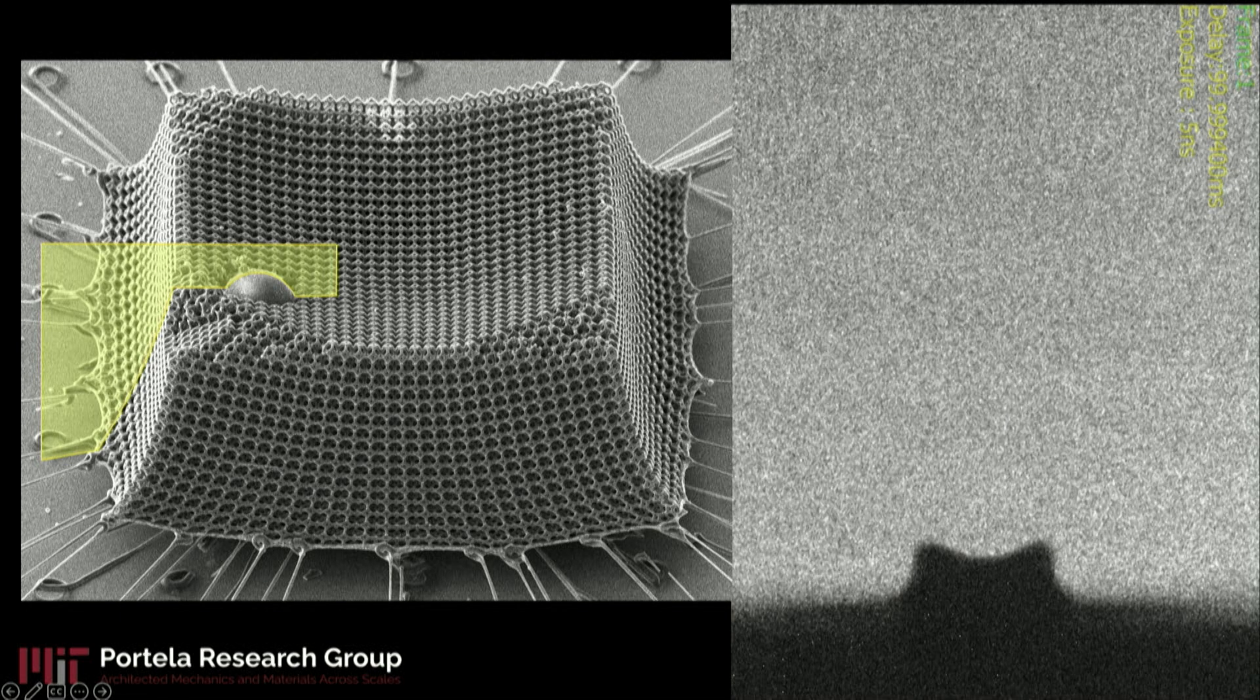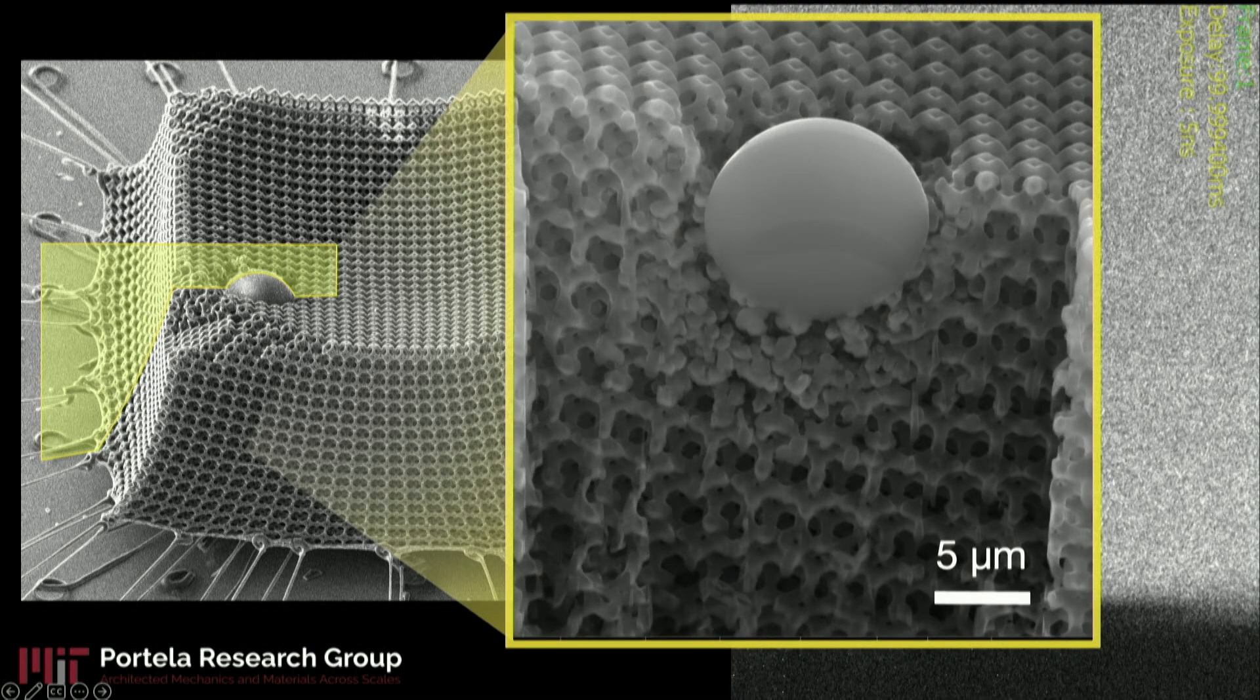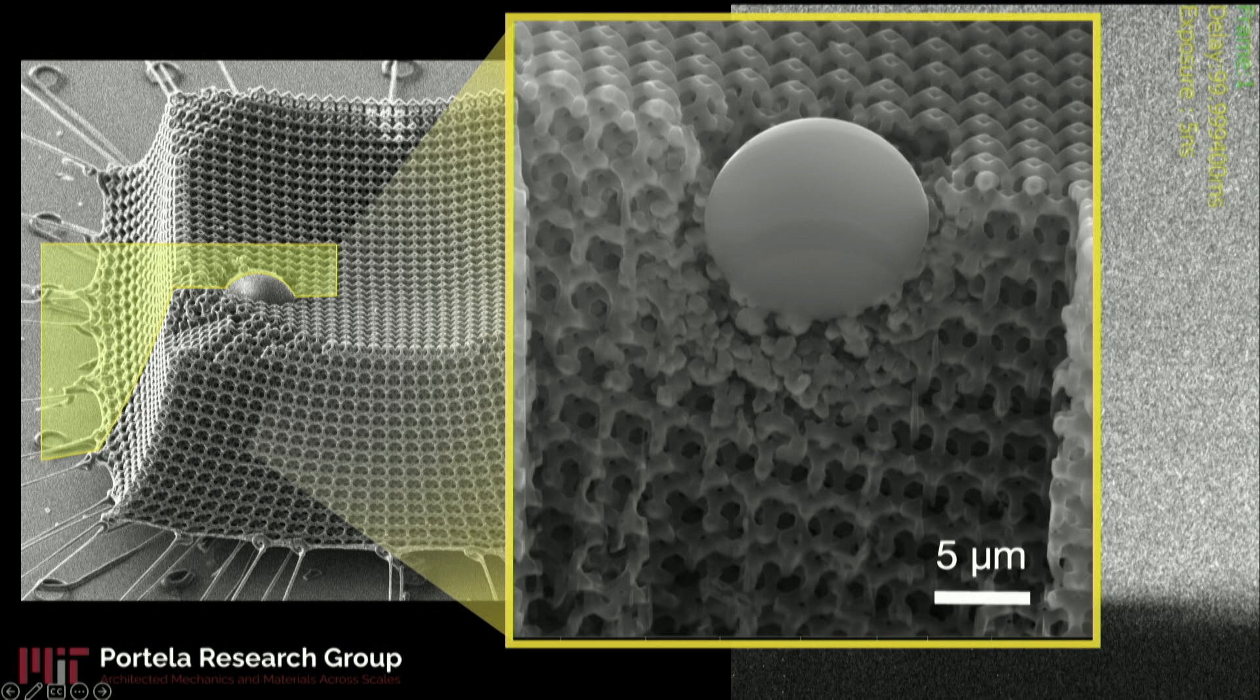We could take a closer look. And indeed, you see that a lot of this energy dissipation came because we were able to crush the material under it. We're also able to do a quantitative analysis, and we're able to find that these materials are about 70 percent more effective at dissipating energy than typical Kevlar per unit mass.